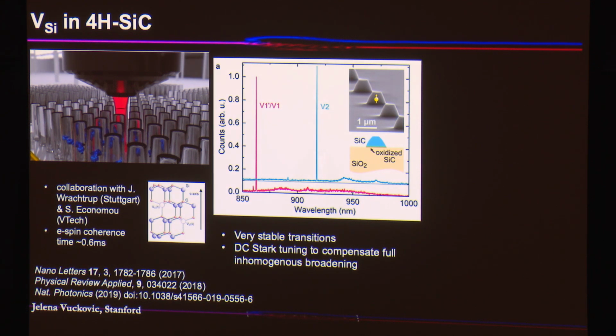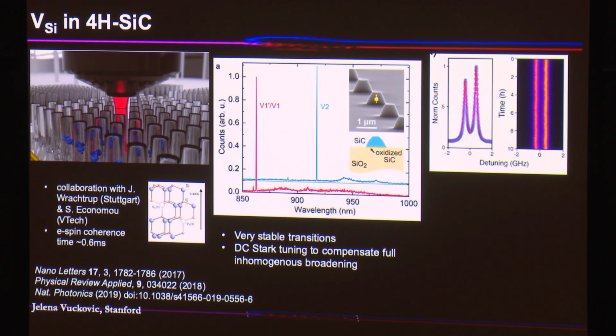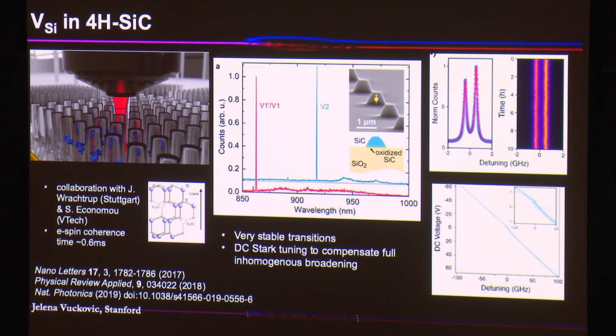There are a lot of different polytypes of silicon carbide. We like this one. This one hosts the most interesting color centers, in our opinion, and most of the groups doing quantum optics work on this particular polytype. It has nice properties. It has nice color centers in the range around 900 nanometers, same as the quantum dots that we used before. We can see that they're pretty stable. This is over hours, 10 hours for this particular V1 transition. And it's just a single missing silicon atom that is producing this particular color center.